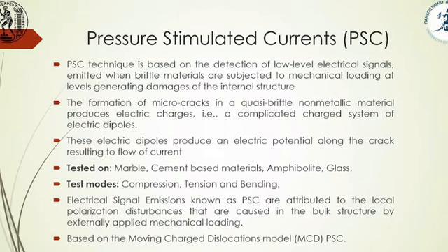And regarding the pressure stimulated currents, it is a non-destructive testing technique, which is based on the emitted electrical signals, which could be attributed to local polarization disturbances that are caused in the bulk structure by an external applied mechanical loading.